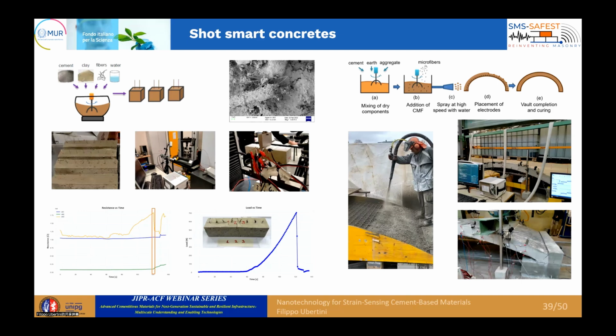We developed the material for spraying, like we are showing in this picture of the test we did in the lab. And we sprayed an entire vault, let's say a shallow vault like this one, made of this smart earth concrete that we tested until failure. First, we tested with uniform load coming from water-filled elements, and then applying a force at 1/4 of the span of the vault.